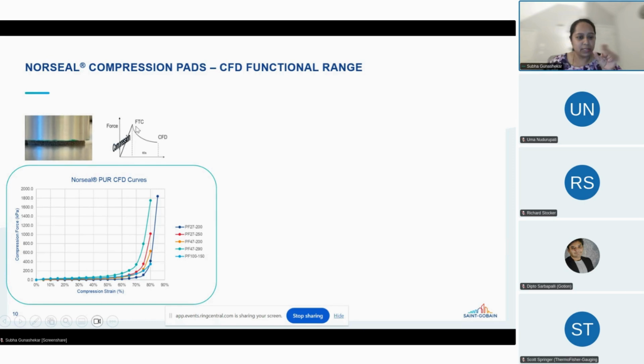The initial compression is your force to compress, and then if you hold that at the same strain rate for about a minute, there is some stabilization. Your force value falls and then it becomes stable. So at the end of a minute, we measure the stress again, and that's called the compressive force deflection. And here you see a stress strain curve of several of the polyurethane foams, which I just spoke about.